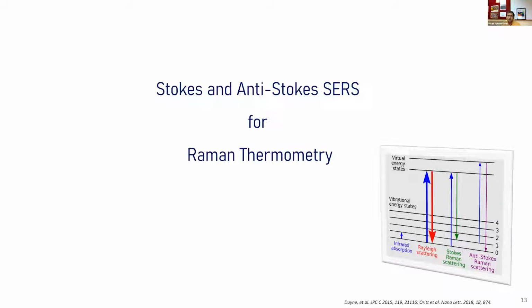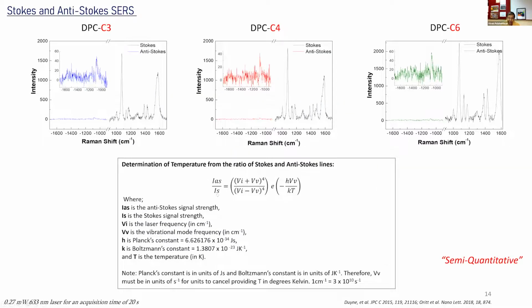So then the question is, how do I measure the surface temperature of a nanoparticle? We're at a nanoscale, so I cannot really use the typical thermometry to understand the surface temperature. There is a technique called Raman thermometry, which monitors the Stokes and anti-Stokes lines in the spectrum. We know that if the molecule is thermally excited, then you will have more population in higher vibrational states, and if that is the case, I will get more anti-Stokes lines. So by taking the ratio of anti-Stokes versus Stokes lines, where all the other factors are constant, you can get temperature T. There are always some assumptions, so we call it semi-quantitative, but still one of the best methods reported to date to get the surface temperature.